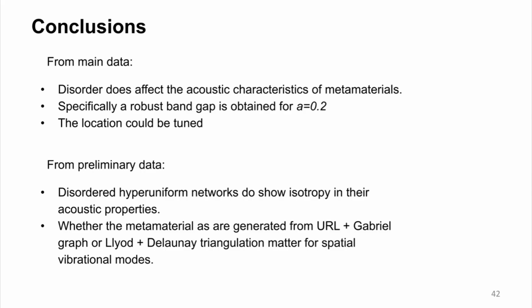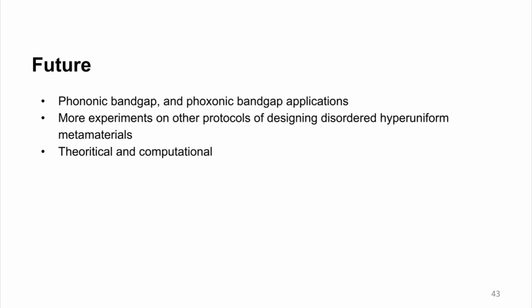And preliminary data also shows that some of the metamaterials generated from Lloyd's iterations and Delaunay triangulation could be used and further studied for spatial distribution of vibrational modes, and also that disordered hyperuniform metamaterials do show isotropy in their acoustic properties. And the future scope is that some of these metamaterials could be made using both phononic and photonic materials, in which way we could combine the band gaps seen in the photonic region and phononic region and create something called phoXonic band gaps.